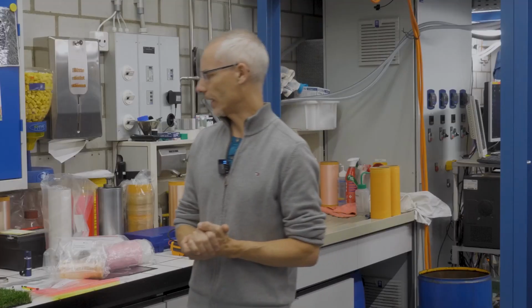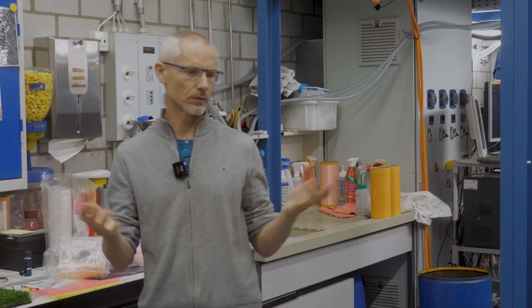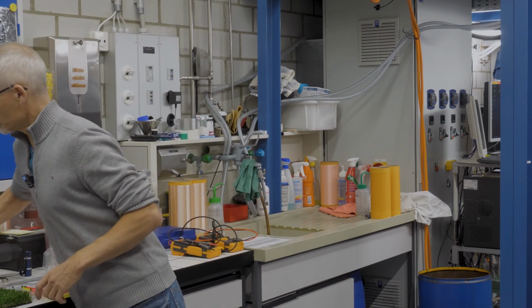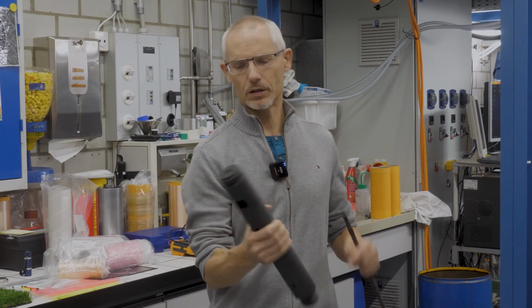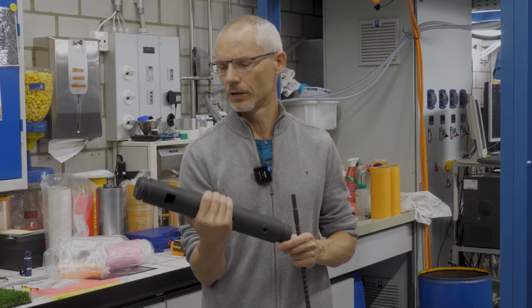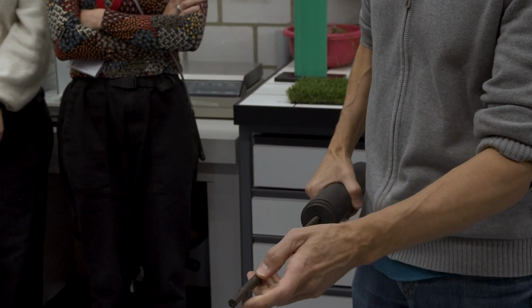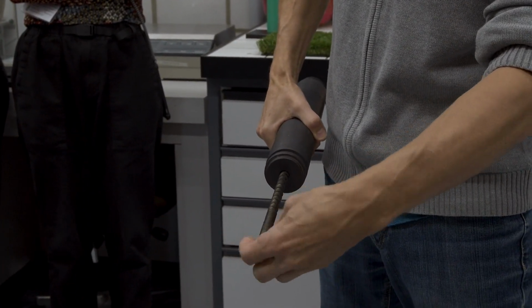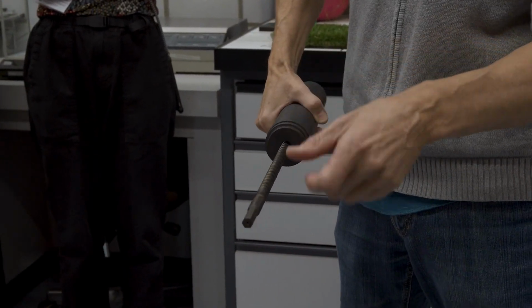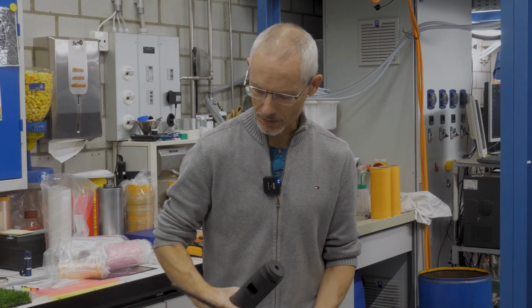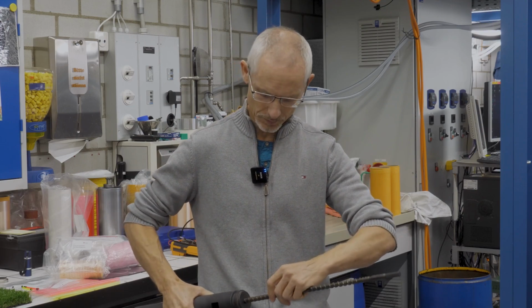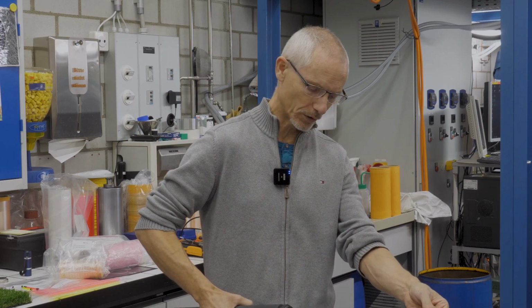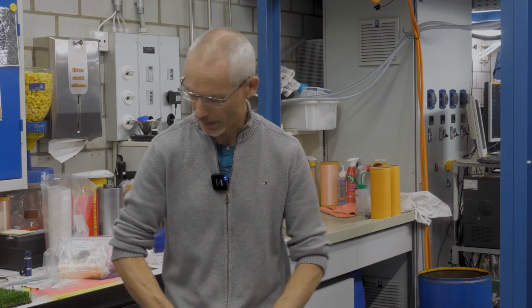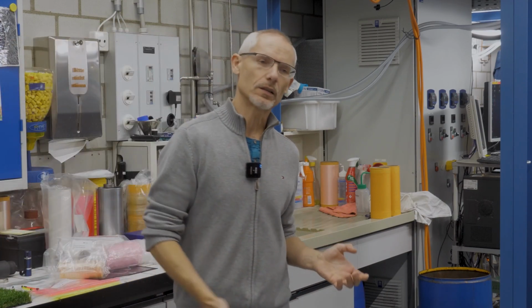How can we achieve such fibers? So what we first need, we need to melt the polymer and pressurize it. For that, we use an extruder, which is kind of a tube which we can heat from outside, either with oil or with electricity. And then in the tube, we have a screw, with special design. The screw turns, and by turning, we transport the polymer within the tube. The polymer melts, and since the area, or the volume that the polymer has within this screw and the tube gets smaller and smaller, we also pressurize the polymer. So in the end, we have a polymer melt under high pressure. And we are talking here about pressures that in the end we have over the spinneret of 50 to 150 bars, so really high pressures.